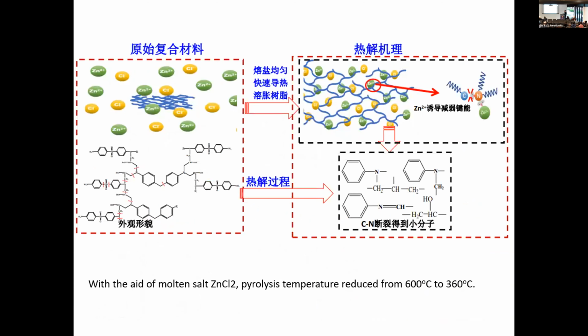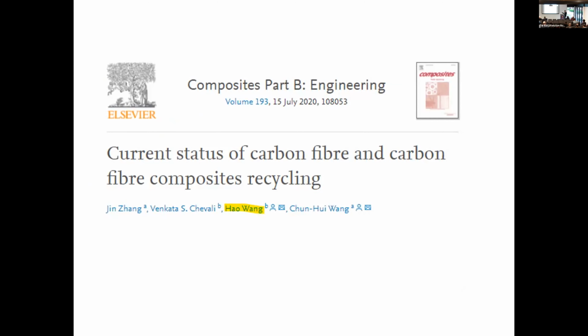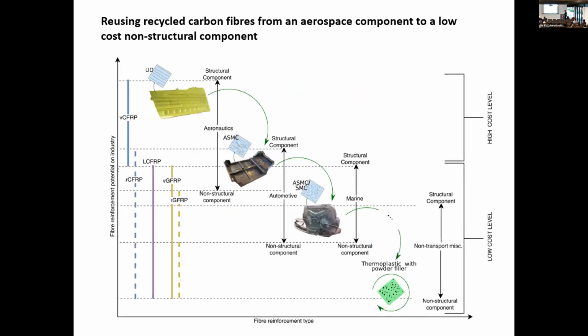What we do is add some catalyst to further reduce the pyrolysis temperature from 600 to 360. That means the energy for pyrolysis is lower, and the recovered carbon fiber is of better quality. We wrote a paper particularly on carbon fiber recycling and carbon fiber composite recycling. There are several stages: from continuous carbon fiber in aerospace, you can recycle to non-structural applications, go to automotive, and even go to plastics as filler. So you can have several stages, as mentioned in the paper.